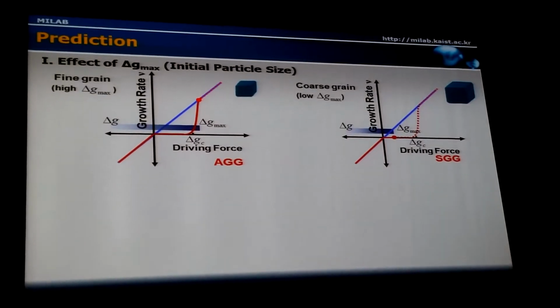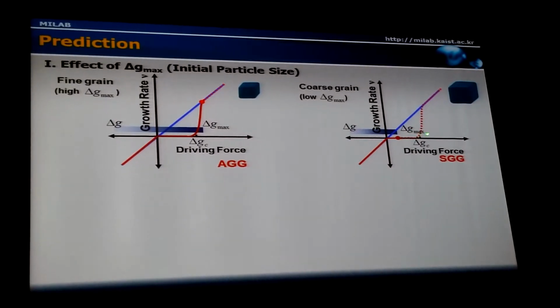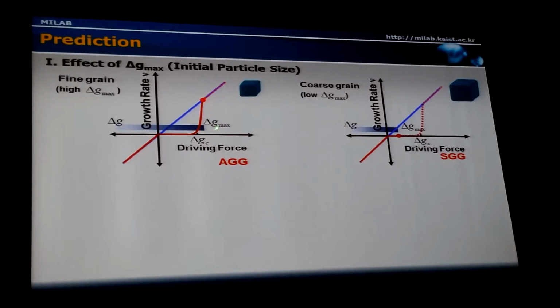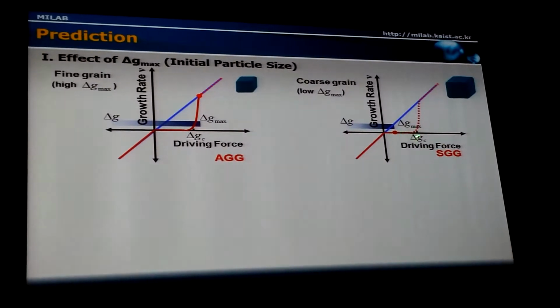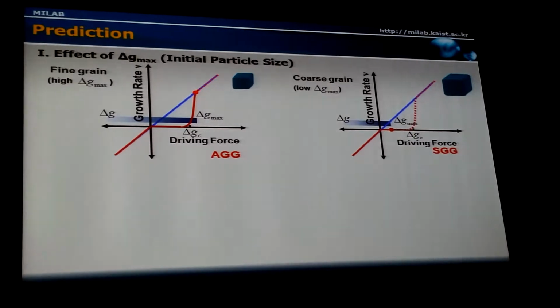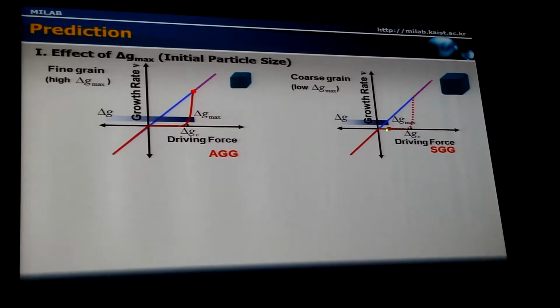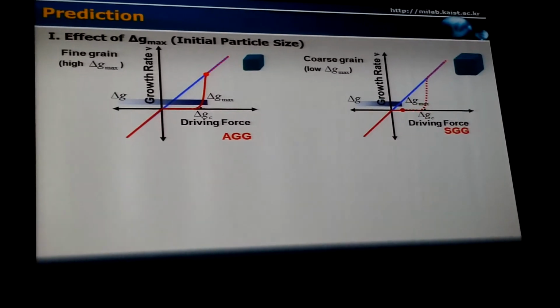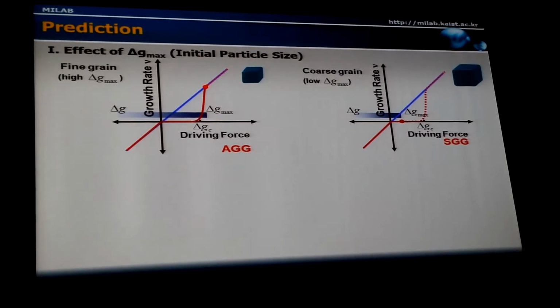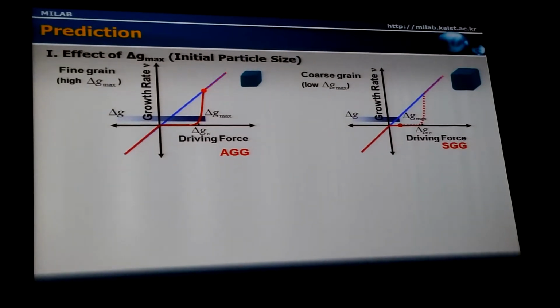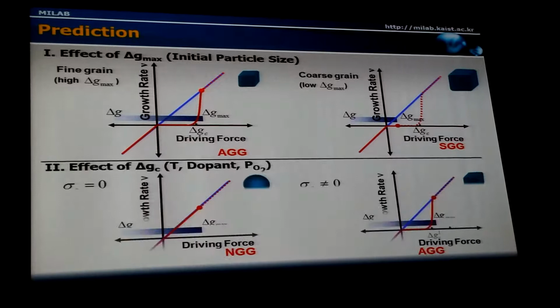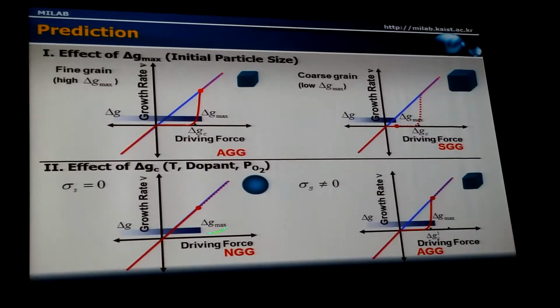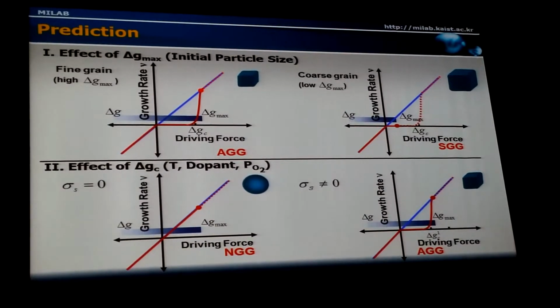On the other hand, in the case of coarse grains, the maximum driving force can be lower than the critical value, and then none of the grains will grow appreciably because their growth rate is almost nil, showing stagnant grain growth behavior. We can also predict the effect of the critical driving force for the same average grain size.